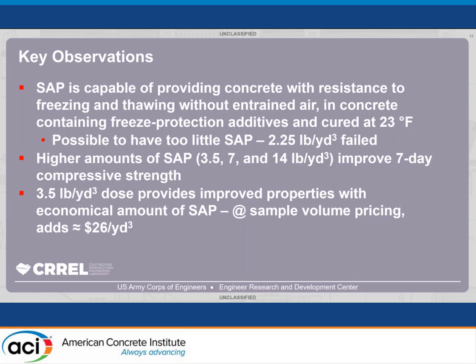So we could try another value higher than that, but lower than the second highest, and see if we could find a threshold of where it's just not enough. But what we found from our small scale research was that the lowest dosage of 2.25 pounds per yard was just not enough. And as I said, as you move more into the 3.5, 7, and 14 pounds per yard, we saw an improvement over the control for the 7-day compressive strength, and then again for 28, and then on to 90.